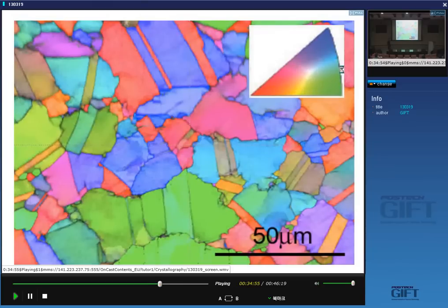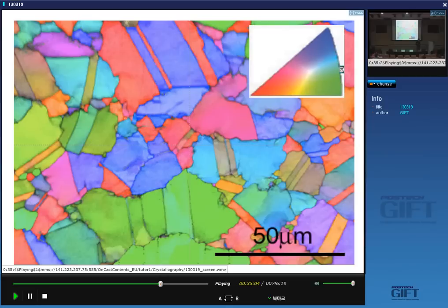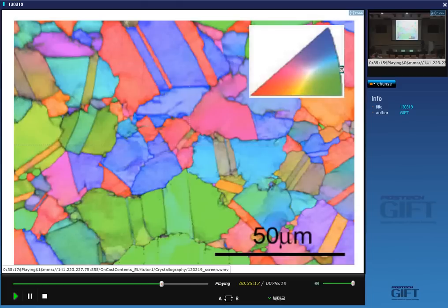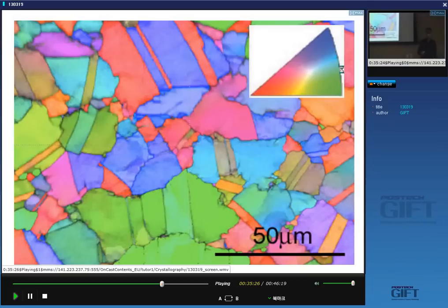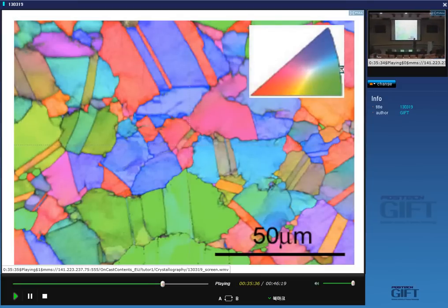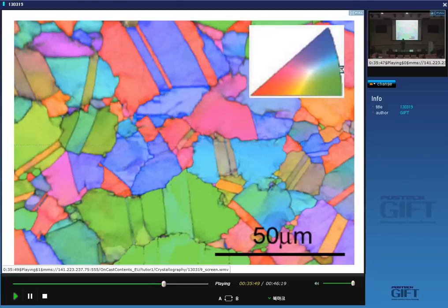With EBSD you have absolutely all the data you need in the files — the orientation of every single crystal and where they are located. You know that neighboring grains are adjacent and can get orientation information for each. This is an extremely powerful technique: you not only have texture but also microstructure. Unfortunately, like many modern techniques where you have all the information, most people do not make use of it — they are happy to get the color image. But if you measured a thousand crystals, you know absolutely the orientation and neighborhood of each crystal, and there is a lot to gain by doing more detailed analysis.